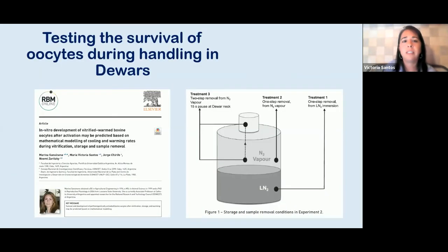Now we wanted to test the survival of bovine oocytes during handling in dewars, and we applied 3 treatments. Treatment 1, a one-step removal from liquid nitrogen. Treatment 2, a one-step removal from nitrogen vapor. And treatment 3, a 2-step removal with a 15-second pause at the dewar neck.